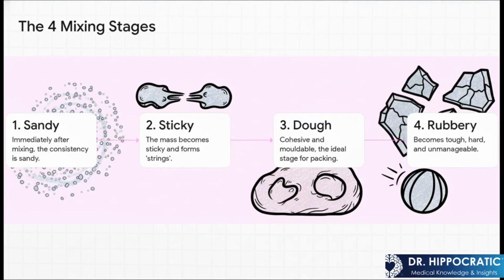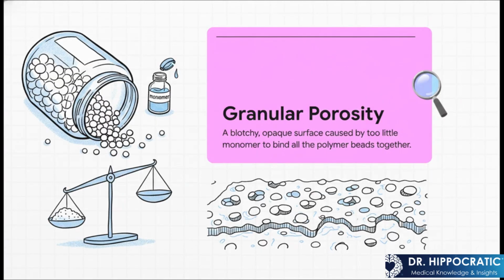As you mix them, the material goes through these 4 really distinct stages. First, it feels sandy. Then it quickly becomes sticky, and it'll form these little strings if you touch it. Next up is the magic moment, the dough stage. It's just like modeling clay. This is the perfect time for packing. But you have to be quick, because if you wait too long, it becomes tough and rubbery, and you've completely missed your window. And this right here, this is our first potential point of failure.